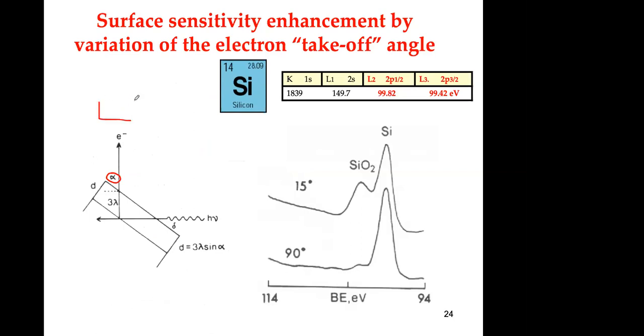So your analyzer is here to detect the kinetic energy of the electron. Depending on the angle, you will see more of the surface or less surface. So here, if you put this at 90 degrees, it's sort of in this direction. So the penetration is deeper. If you put it in this direction, then this distance is the same as this one. So here you will see deeper, and you will see mainly silicon and not the oxide. Meaning that if you decrease the angle, you see this silicon oxide. Since you don't see it at 90 degrees, it means that it's a very thin silicon oxide layer on silicon. So in order to enhance the surface, you can just change the angle, and that will really help you analyze the sample better.